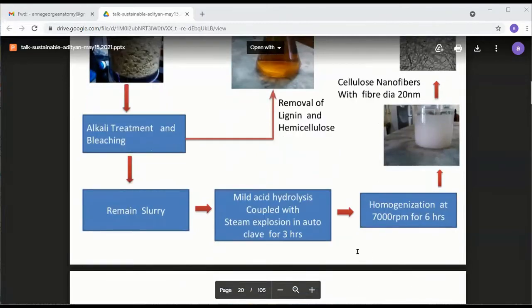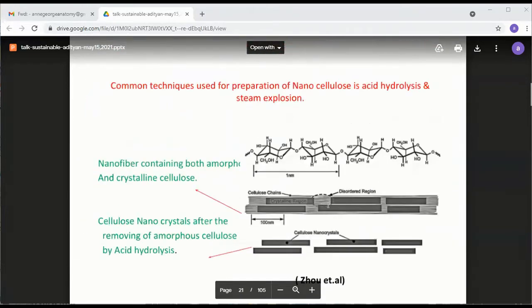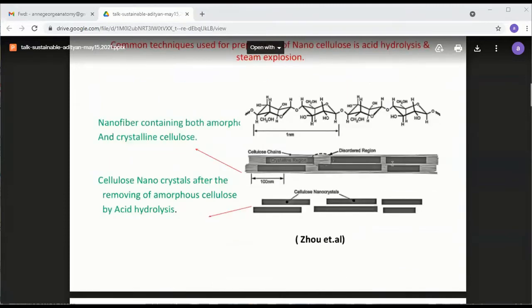You can make either long nanocellulose. You can also make short nanocrystals. The difference is when you have a long nanocellulose, you have both amorphous and crystalline segments coexisting. If you look at nanocrystal, you don't see any amorphous part because you have used a strong acid. You kill all the amorphous part. So dear friends, you have two options. Either you can make long nanocellulose or you can make short nanocrystals. You have two possibilities. If you use strong acid, you get short nanocrystals.